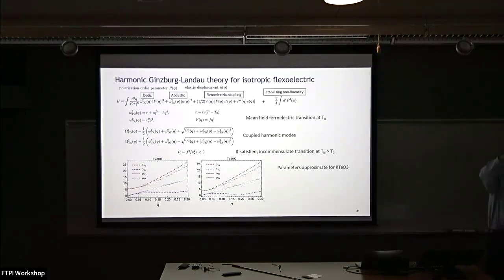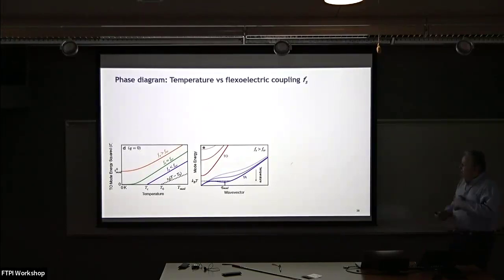You can go from the normal phase into a ferroelectric phase via an intermediate phase, which is incommensurate. It's in fact very common that there are phases which have, if you look, very long period order on the edge of ferroelectricity. It's kind of a standard thing. It's actually quite well known because this coupling can in fact be big. So let's ask, in fact, what might happen as a function of the phase diagram.